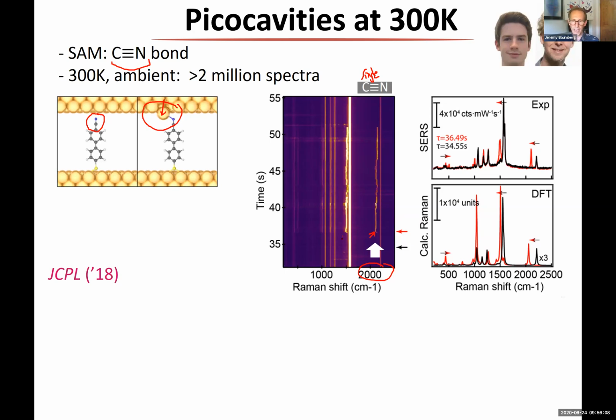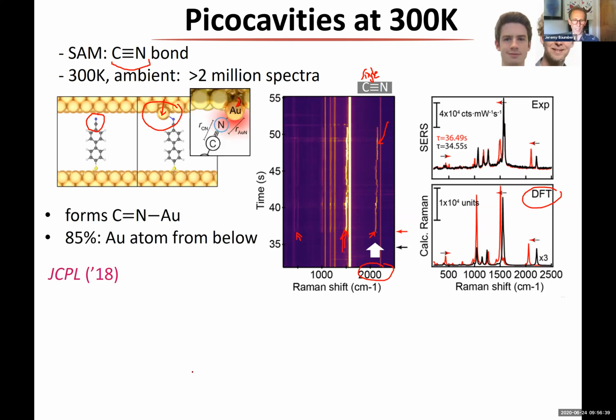You can also see that the ring modes also shift around because, of course, they're electronically coupled, and there's lots of features going on in here. We can actually use DFT to match very well what's going on. And indeed, it's exactly what we predicted. There's a coordination bond between this gold atom here and the nitrogen. So we can measure the strength of that. And what's happening here is that the strength of that bond is varying around in time on milliseconds to second timescales. So we're still trying to understand why that is.